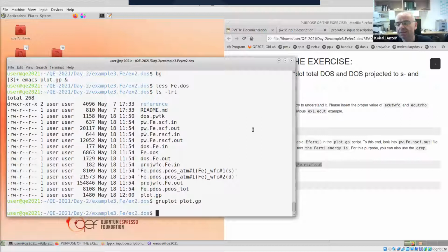So I think that for both, of course, with these K points, we need to have some provision. If I compress the structure, and for example, the structure becomes metallic, then of course this K-point convergence can be significantly affected, because we can go from non-metal to metal. But these are, let's say, special cases. Normally, I would say that the K-point convergence does not critically depend on the lattice parameter, and taking the experimental lattice parameter would be just fine. This would be my answer to this. Okay.